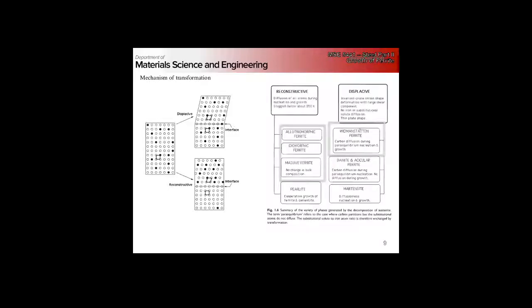So we have two main classes of transformation — not mechanisms, because each one has its own different mechanisms, but two main classes: reconstructive, which are basically diffusion-mediated transformations, and displacive, which are transformations that involve an invariant plane strain.